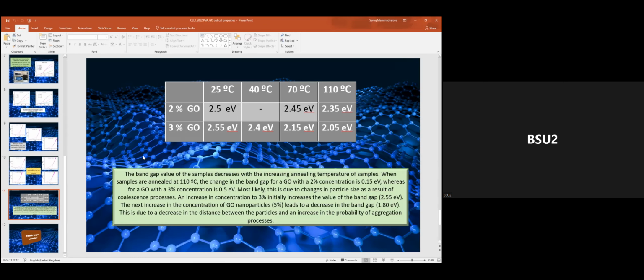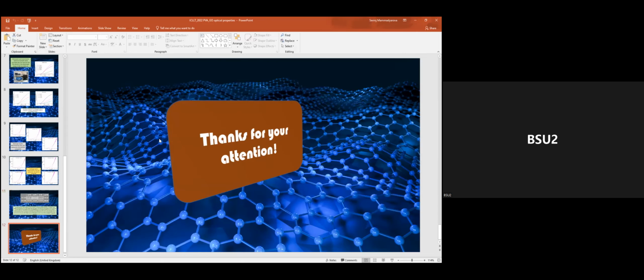The next increase in the concentration of graphene oxide nanoparticles, 5% concentration, leads to the decrease in the band gap, 1.80 electron volt. This is due to decrease in the distance between the particles and an increase in the probability of aggregation process. Thanks for your attention.